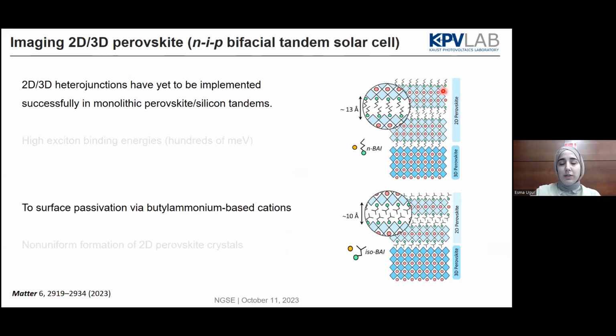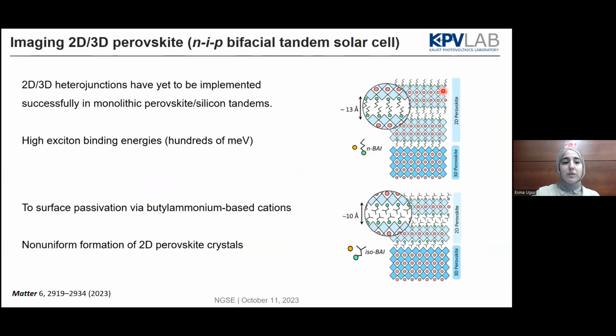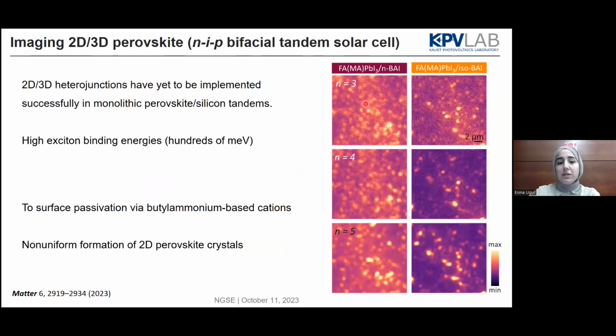We basically checked again with the PL. As I mentioned, we need to deal with this high exciton binding energy since the light is coming from the top. What we have is the non-uniform formation of these crystals. You can see some regions, up to maybe 1 micrometer, where you see the formation of these excitonic peaks, while the rest is darker. This PL maximum and minimum gives us information that it is on the surface, not on the whole film, so that's why you can easily see the formation of these excitonic peaks.